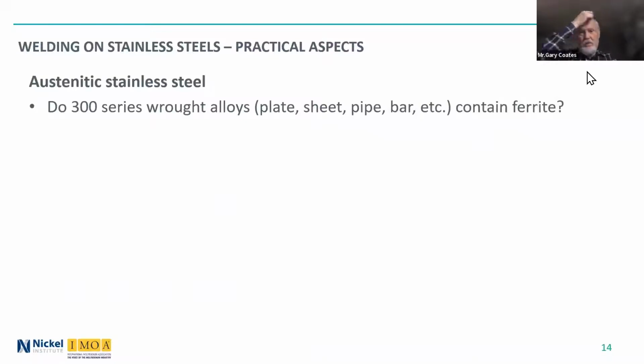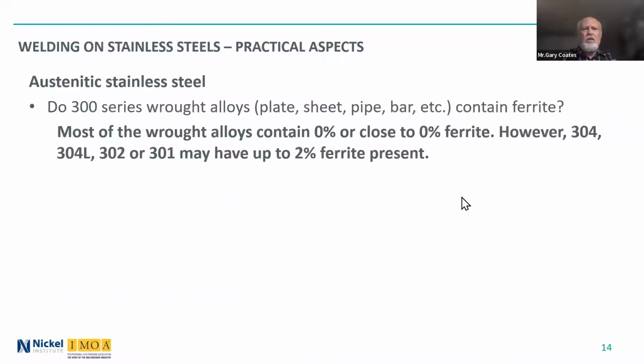So I'm going through a series of questions here. Do 300 series wrought alloys, plate, sheet, bar, pipe, etc., do they contain ferrite? And the answer is basically most of the wrought alloys contain 0 or close to 0% ferrite in them. 304, 304L today especially may have up to 2% ferrite present. So it is the exception that people are keeping the chromium, the nickel content, and in molybdenum containing grades, the molybdenum content right down at the bottom end of the specification. And that has meant that, especially the 304 grades, they may have up to 2% ferrite present.